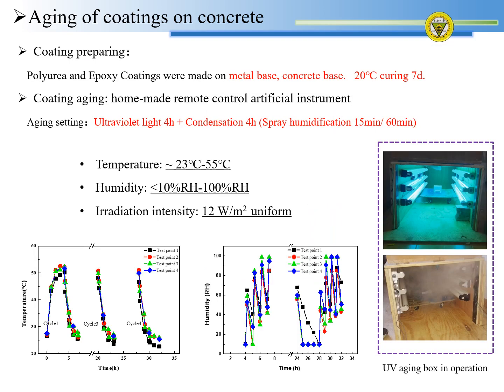Let's see some details in experiment procedures. We choose 2 kinds of coatings, epoxy resin and polyurea resin. These 2 coatings are widely used in current engineering applications. After curing, the setting of aging is here. 4 hours ultraviolet irradiation and then 4 hours condensation. Every 8 hours is a cycle.